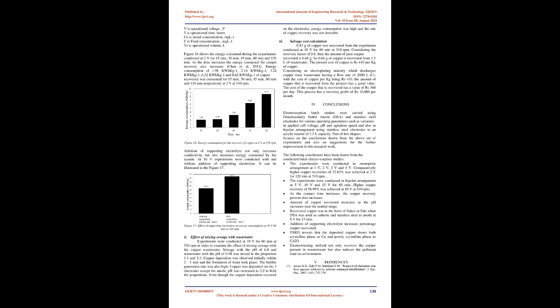Figure 16 shows the energy consumed during the experiments conducted at 2V for 15 minutes, 30 minutes, 45 minutes, 60 minutes, and 120 minutes. As the time increases, the energy consumed for copper recovery also increases (Chen et al., 2013). Energy consumption of 1.98 kWh/kg, 2.14 kWh/kg, 3.24 kWh/kg, 6.32 kWh/kg, and 8.62 kWh/kg of copper recovered was consumed for 15 minutes, 30 minutes, 45 minutes, 60 minutes and 120 minutes respectively at 2V at 510 rpm. Addition of supporting electrolyte not only increases conductivity but also increases energy consumed by the system.